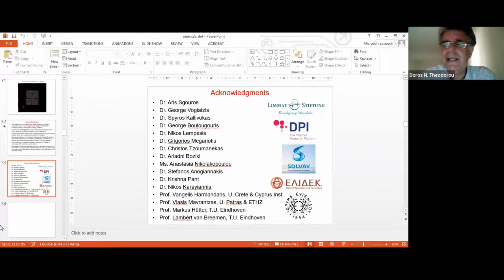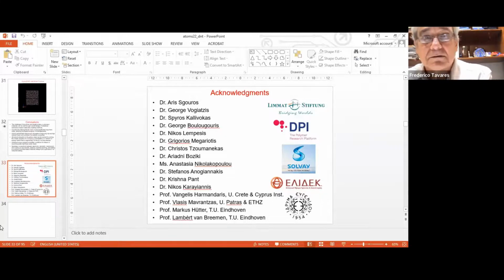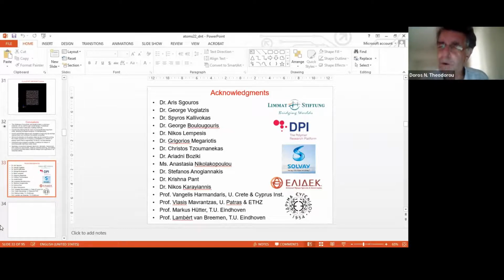Unfortunately, these slip springs have to be introduced there, because on one hand, we cannot do atomistic molecular dynamics for very long chain polymers. We cannot reach the required times. And on the other hand, the mesoscopic model is so soft that the chains can't entangle. In other words, because you coarse grain so much, the potential of mean force is so soft that the chains go through each other. So that's why these slip springs have been introduced. Many people have used them, and they seem to do a good job. The idea goes back to Sam Edwards, who used slip links, as he called them, to describe elasticity of polymer networks. But then people like Masubuchi and Markus Müller used slip springs, and they found out that slip springs would be more realistic, so that is what we're using.